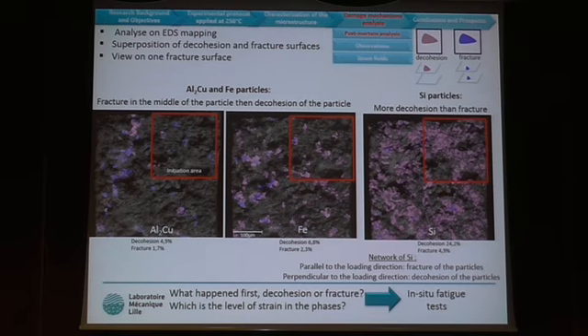So to understand the damage mechanism, we did some post-mortem analysis. Here I show only one part of the fracture surface, and we superpose the decohesion and fracture surface. What they call fracture is when the particle is broken, and you can see the particle on both sides of the fracture surface, and decohesion only on one face, on one side.